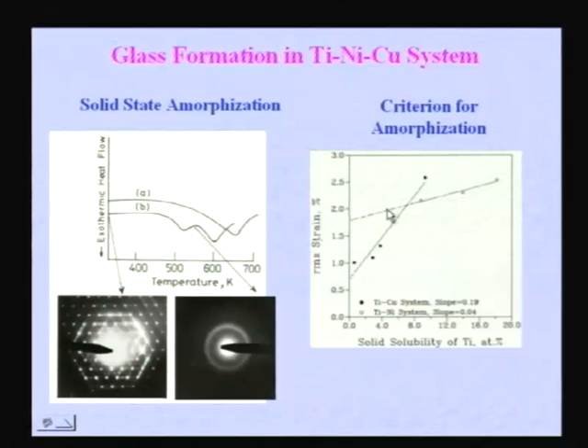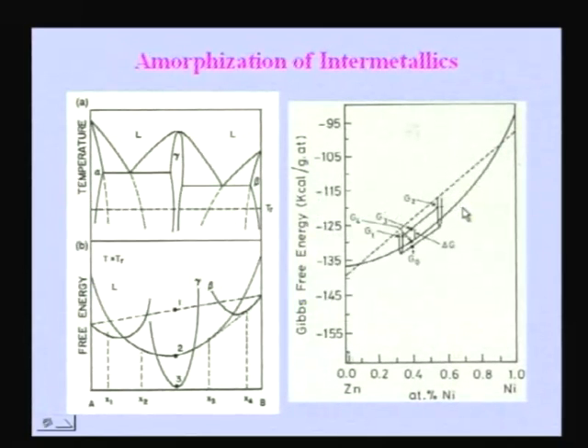This is another criterion for amorphization, the strain criterion which we have talked about before, and this is how an intermetallic can be made into an amorphous. We usually know if you take a system like this, you have two solid solutions on both the ends and one intermetallic in the middle, and if you draw the free energy composition curves, you can see an intermetallic has the lowest free energy. The liquid has a free energy like this and the solid solutions have a free energy like this, so it is easy for a solid solution to become an amorphous beyond the T0 curves. Beyond the T0 curve, the solid has a higher free energy than the liquid, so you can easily get an amorphous phase.